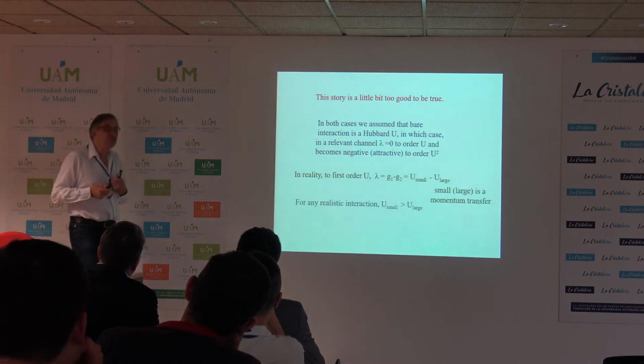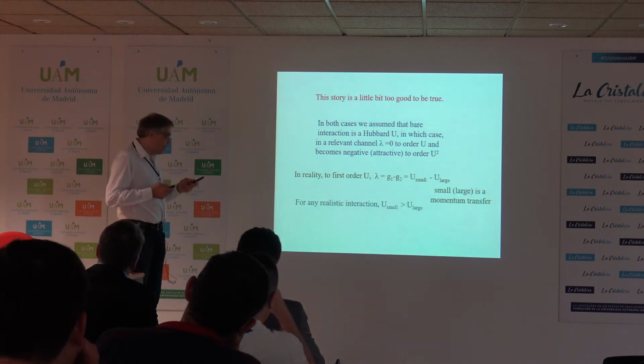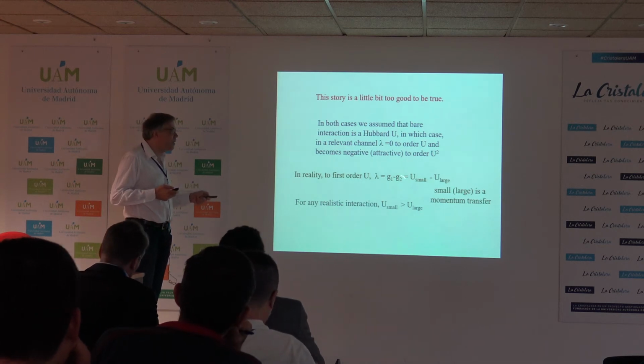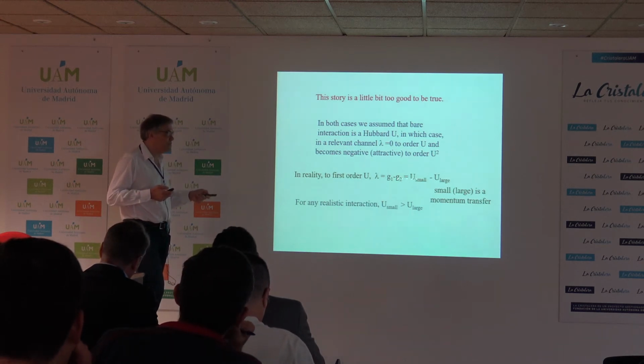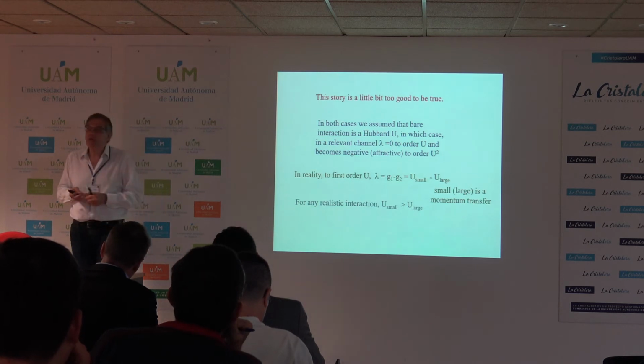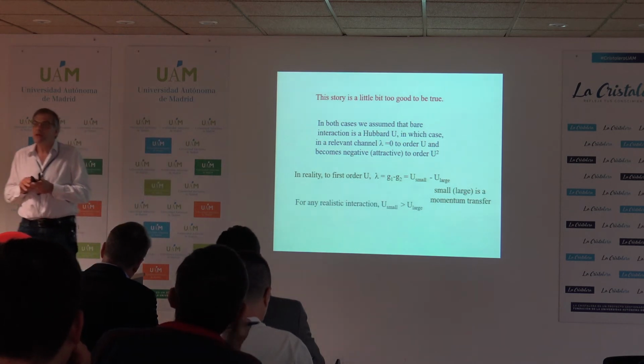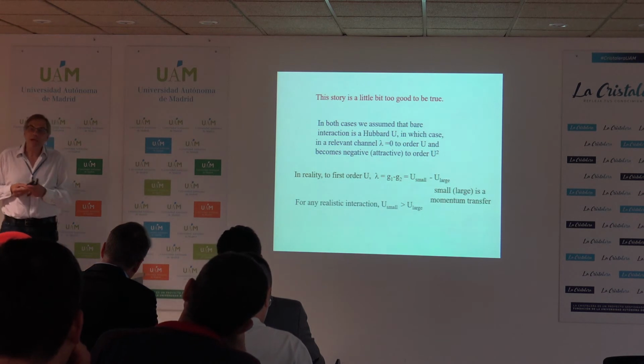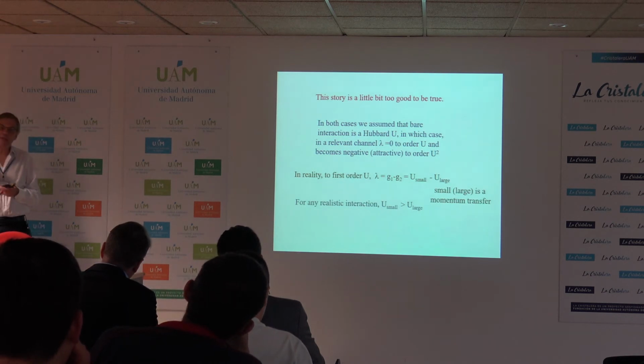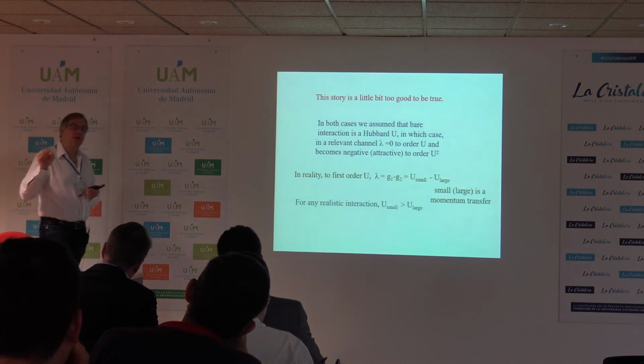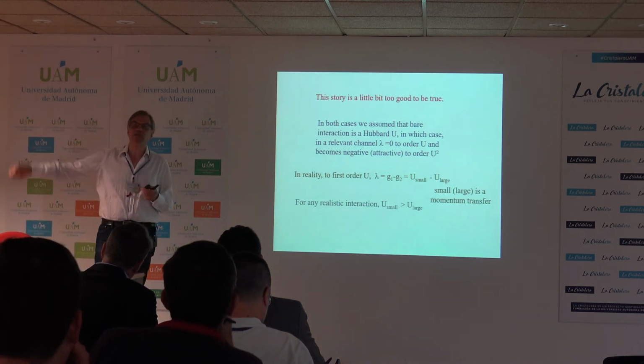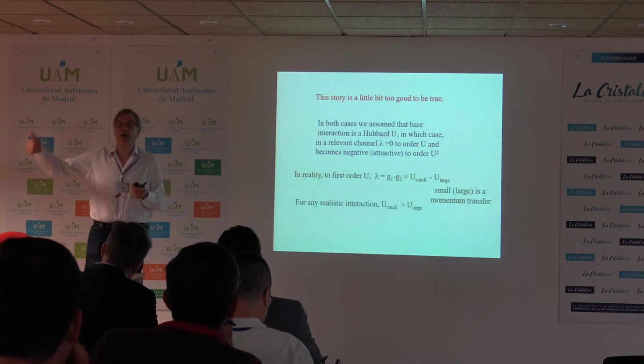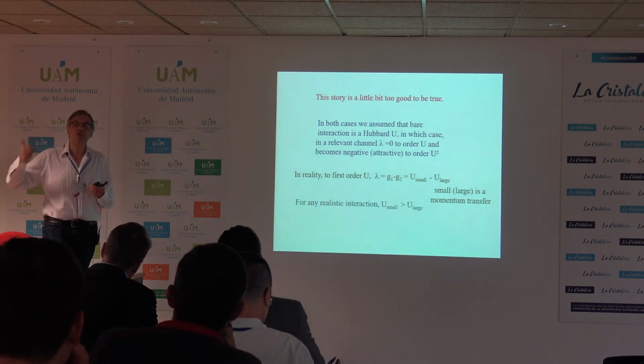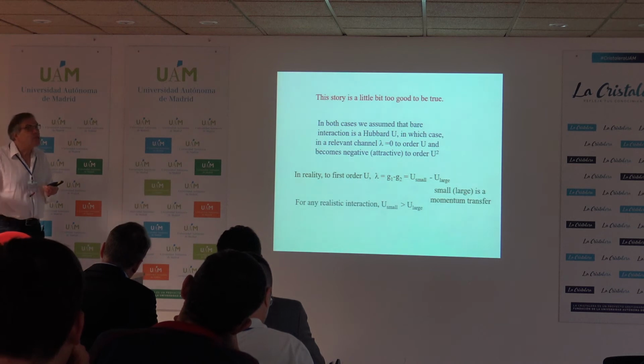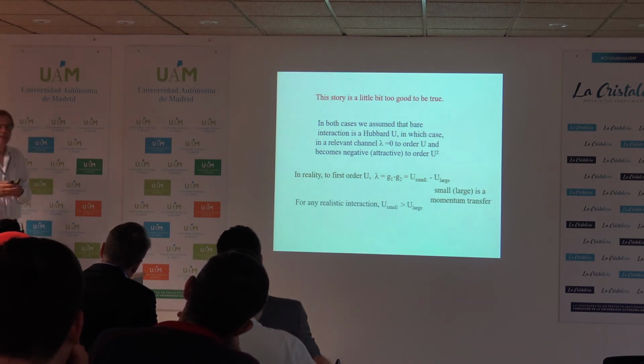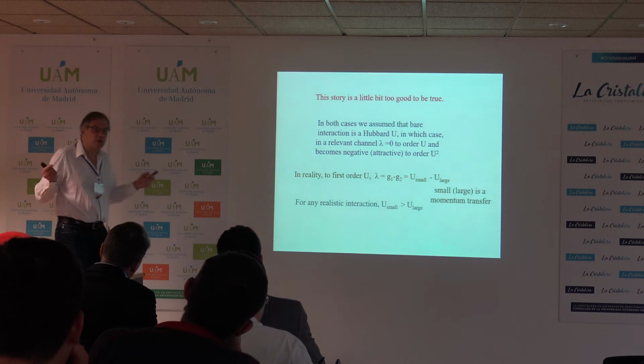So then, if we look at the actual story, we always start with the situation when this lambda is positive. And then the question is, well, what I described to you before is perturbation theory. Then we have a more difficult problem, because we start with repulsive interaction. And we ask the question, how can corrections overshoot this repulsive interaction and convert repulsion into attraction? This you cannot do by just saying, well, I do weak coupling, second order perturbation theory, because then you will get nothing.